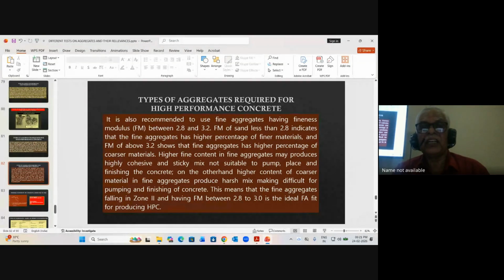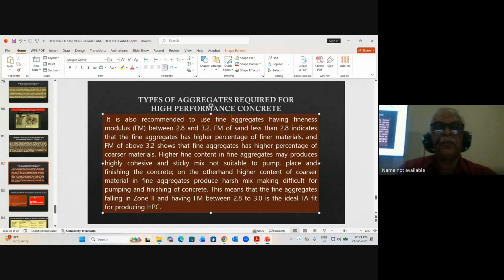And for fine sand aggregate, the fineness of sand should be considered. A higher percent shows coarse material, lower percent otherwise. The ideal should be 2.8 to 3%, which is the ideal fineness for high performance concrete. The acceptable range is 2.8 to 3.2, but ideal is 2.8 to 3%.